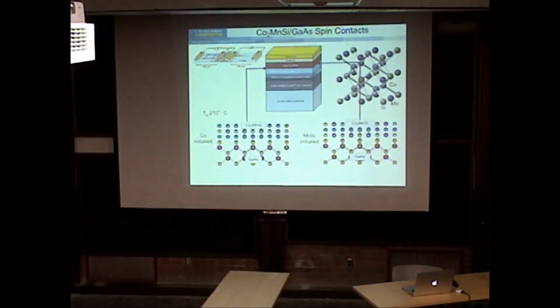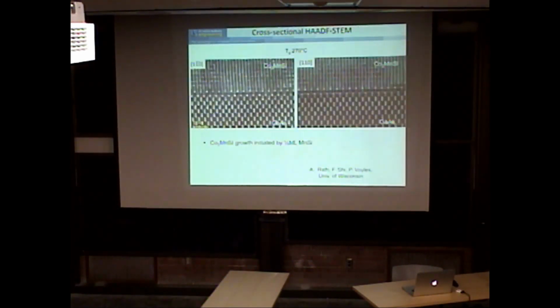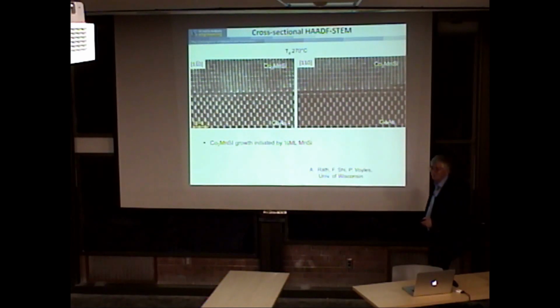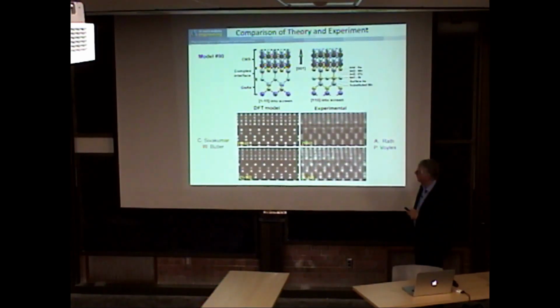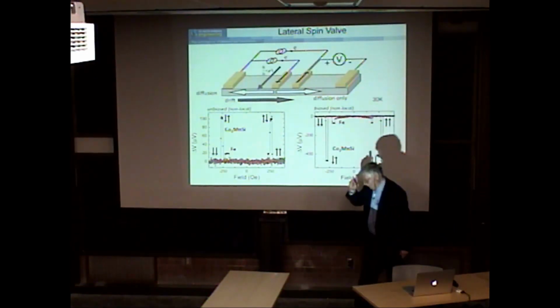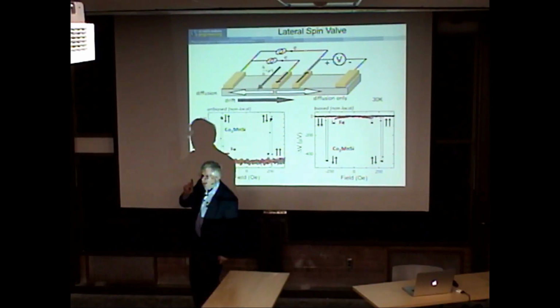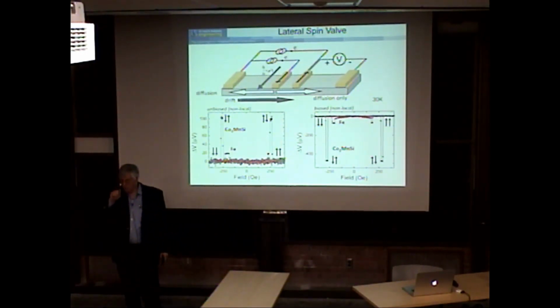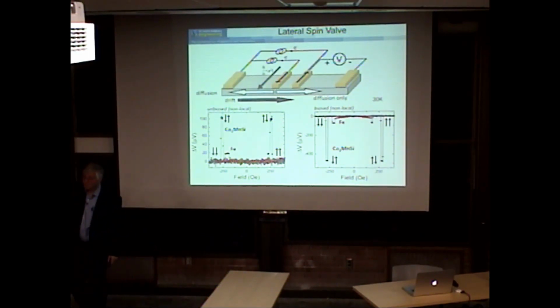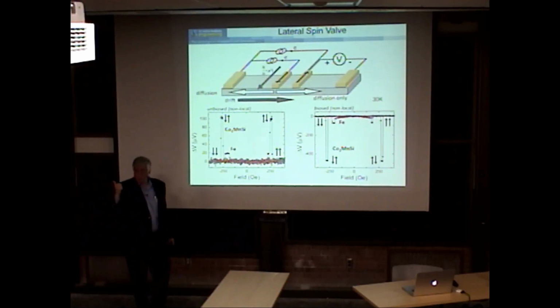What about lateral momentum mismatch between two materials? Oh, yes. If I look at the Heusler, they tend to have the electron pocket, if it's indirect, out at X, which is a pretty good match for going directly into gallium arsenide at gamma. It's not a perfect match in plane. You think of the in-plane momentum mismatch, so at least I've got the pocket in the right direction. If I do another crystallographic direction, I think you may have to worry.